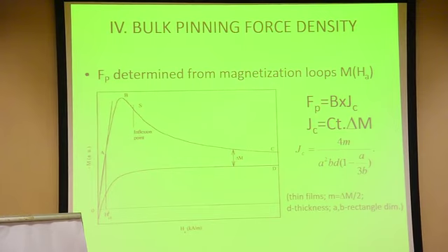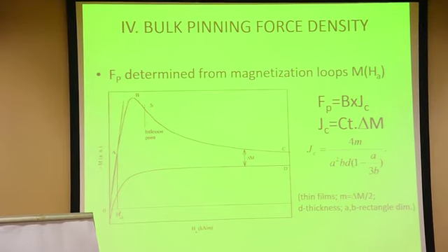And this comes from the well-known critical state model, in which it is assumed that the critical current in a material is constant all over the place, and when the sample is fully penetrated, a lot of things happen. So actually, in this model the critical current density is proportional to the difference in this magnetization. Now, depending on the geometry of your sample, you can have different ways to take JC from this value,